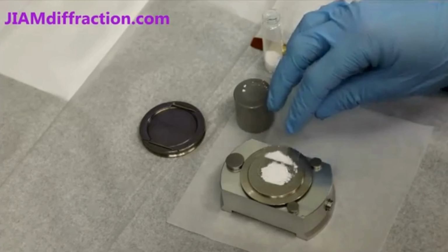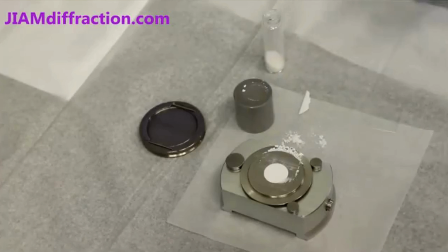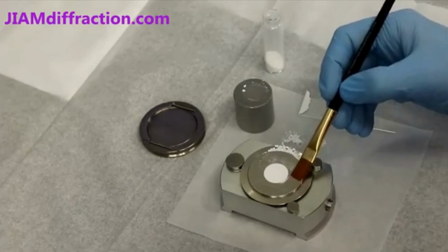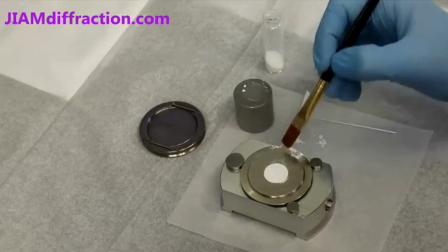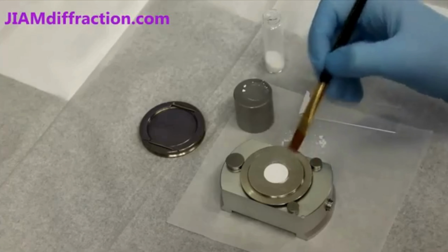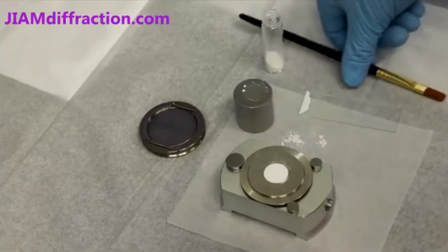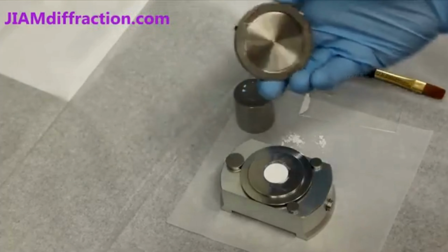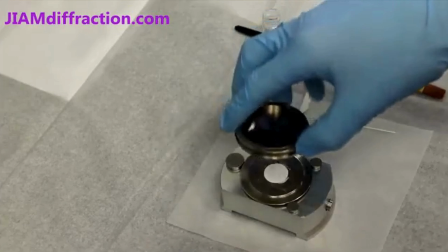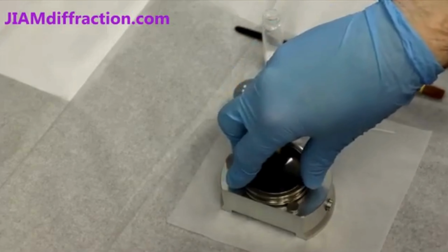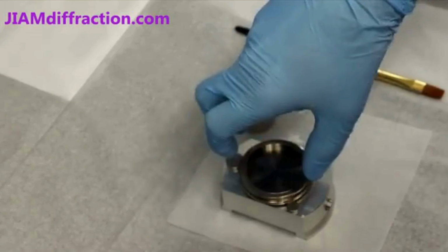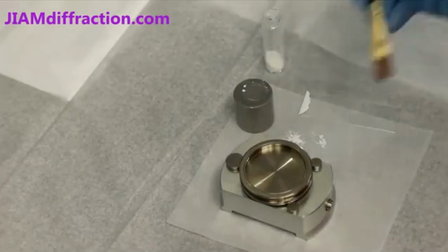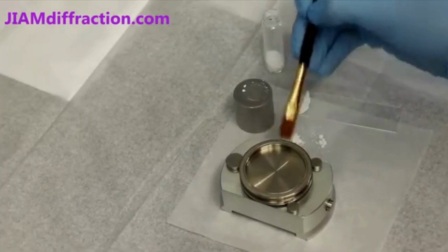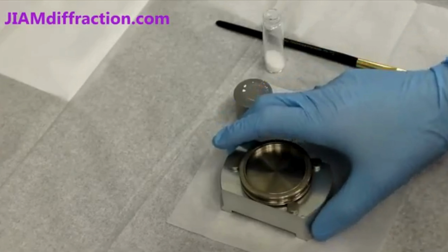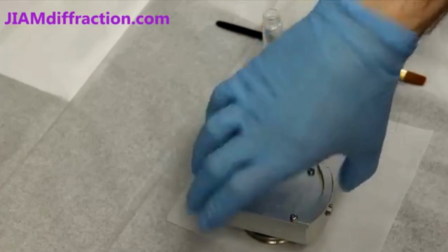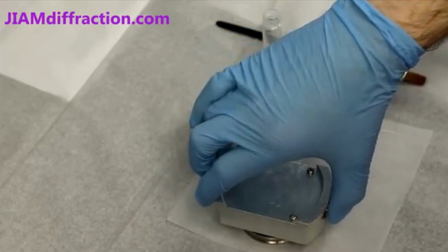Preferred orientation is a major concern in metals, polymers, and layered materials because manufacturing processes often align crystallites along specific directions. Such alignment may suppress certain reflections and produce misleading structural information. Rotating the sample during analysis or reorienting the specimen by 90 degrees can reduce these orientation effects and improve data reliability. Contamination, moisture, and poor sample homogeneity may also degrade diffraction quality. Therefore, careful handling, uniform packing, and optimized alignment are essential for obtaining accurate structural information.